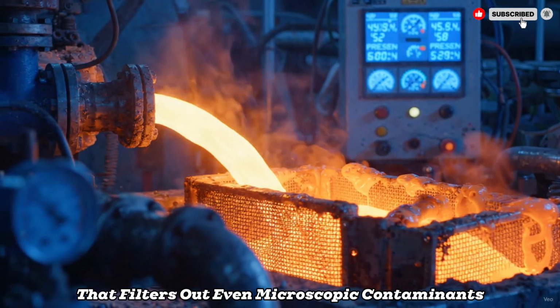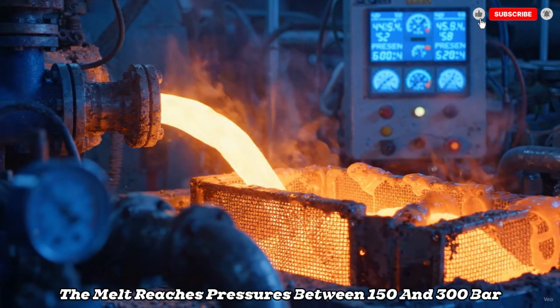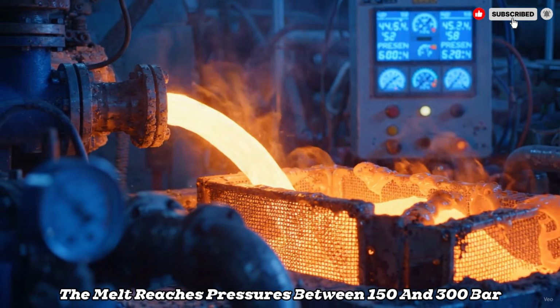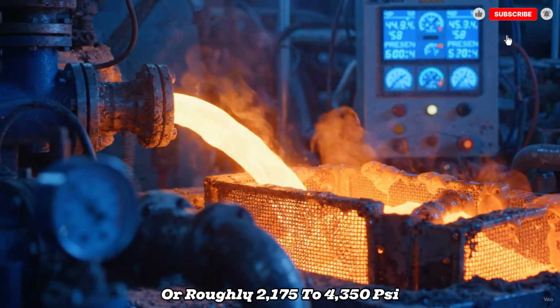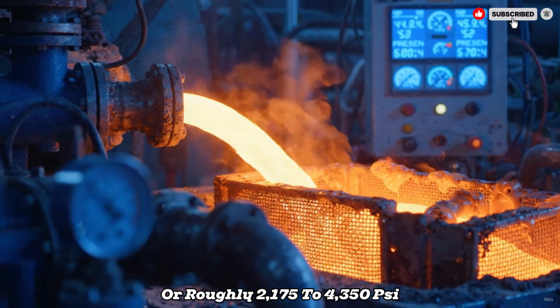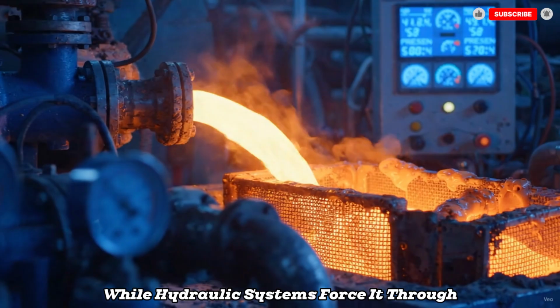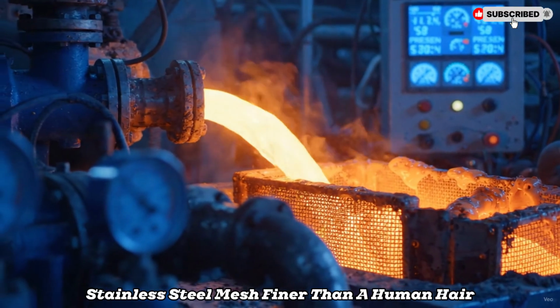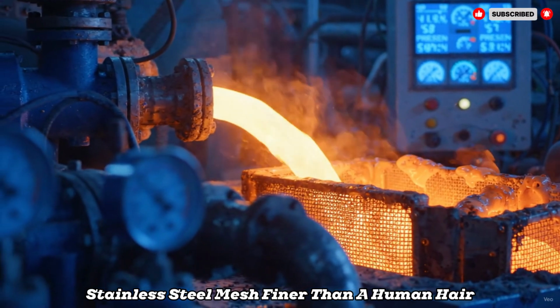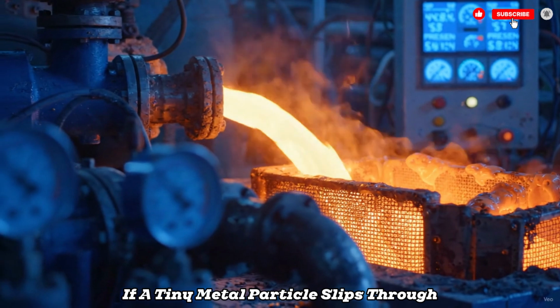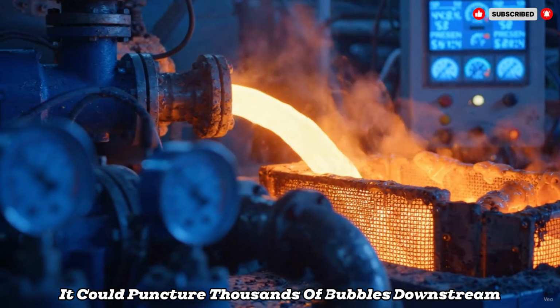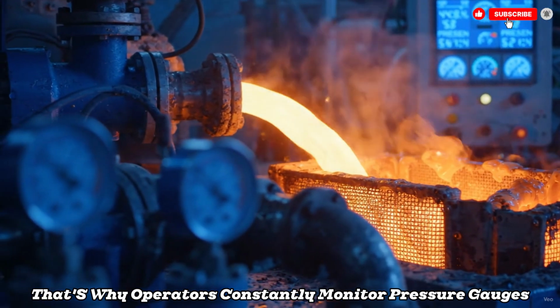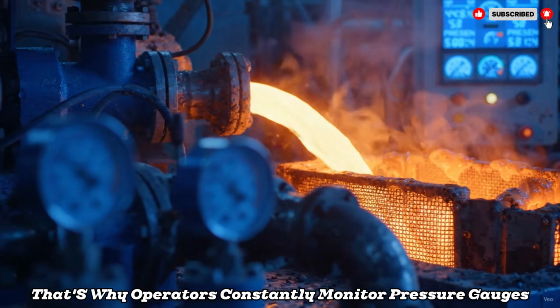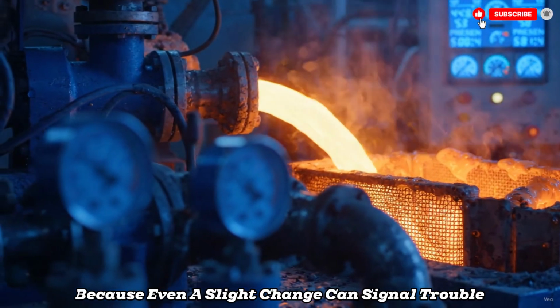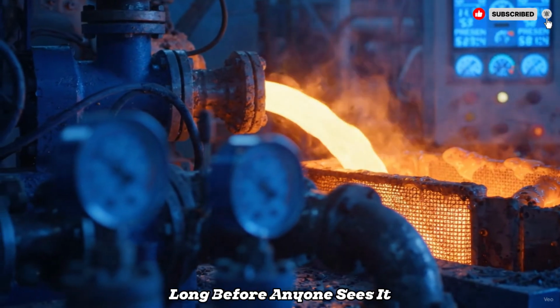out even microscopic contaminants. The melt reaches pressures between 150 and 300 bar, or roughly 2,175 to 4,350 psi, while hydraulic systems force it through stainless steel mesh finer than a human hair. If a tiny metal particle slips through, it could puncture thousands of bubbles downstream. That's why operators constantly monitor pressure gauges, because even a slight change can signal trouble long before anyone sees it.